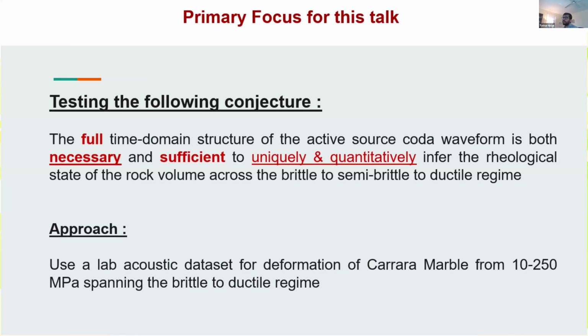So that sets up the conjecture that I'm going to be testing with the results in this talk: that the full time domain structure of the active source coda waveforms is both necessary and sufficient to constrain the rheological state of the rock volume. We want to not only say it can do it, but have a predictive model, because eventually the goal is to have some quantitative rheological model. So I want to test it, not just saying there's a correlation, but quantitatively asking, can you use just the waveform to tell something about the stress state and the strain state of the rock sample? And we want to do this across the brittle to semi-brittle to ductile regime, not just focusing on earthquake friction type perspectives.